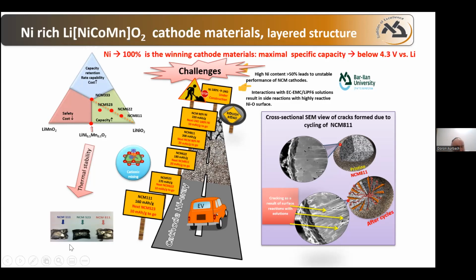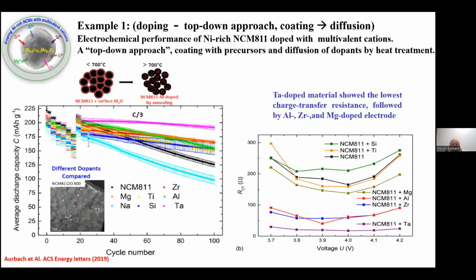Here you can see results of studies by ARC. If we have a small amount of nickel, only 33%, the pouch cell can survive thermal runaway. But when we increase the amount of nickel, we have catastrophes because of instability. So what do we do? We use doping. When we talk about doping, we add foreign elements to these materials, like zirconium, magnesium, titanium, aluminum, silicon, tantalum, and we can use less than 1%, which is effective enough.